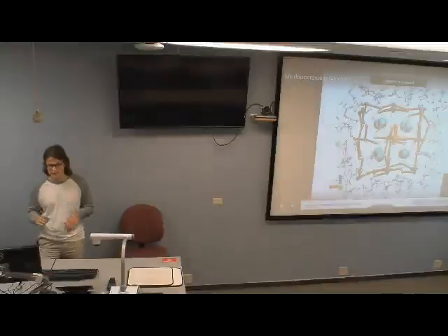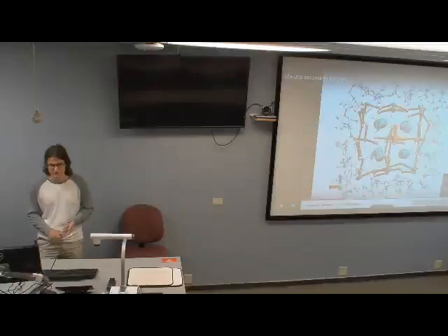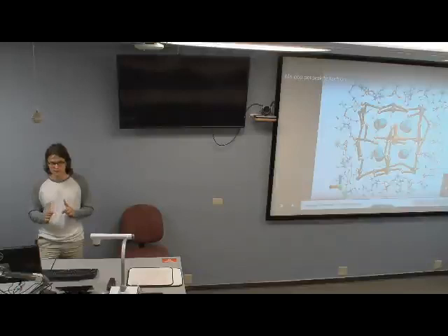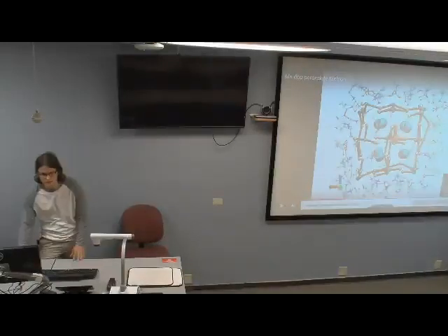I guess the spin states of these dopants is very sensitive to the coordination geometry. So it's probably even going to change oxidation states too if it goes from octahedral to tetrahedral. And so implications for that is like optical stability for its emission, and then also for magnetic properties too. If we don't specifically focus on those, but it's going to change because normally it's in a low or a high spin configuration, and it could just change something completely else.